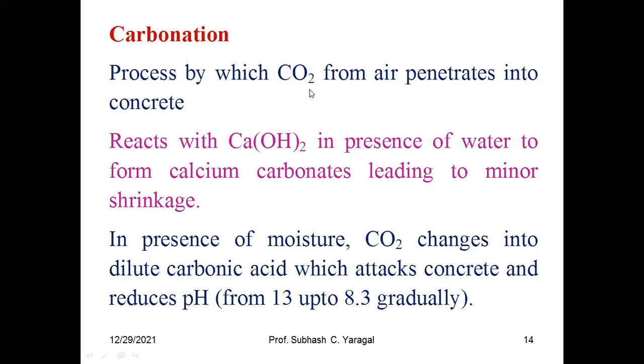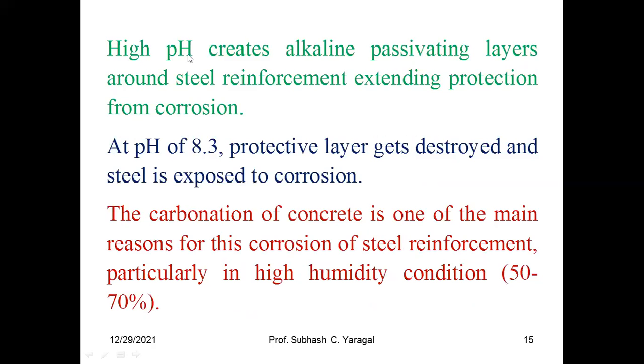Okay. This is the cause of entry of CO2. Again, in addition to that, in the presence of moisture, CO2 changes into dilute carbonic acid. This is of more concern again, which attacks concrete and it reduces the pH from 13 to 8.3. That is, we want the concrete to be alkaline. Due to this carbonation, the pH is getting reduced, that is from alkaline environment to acidic side, due to which again our durability is in question. So high pH creates alkaline passivating layers, which is desired for us around the steel reinforcement, so that steel is not getting corroded, extending protection from corrosion.